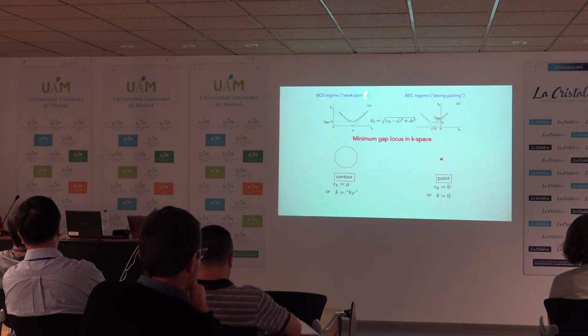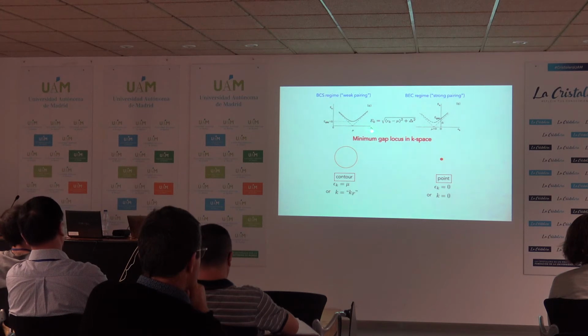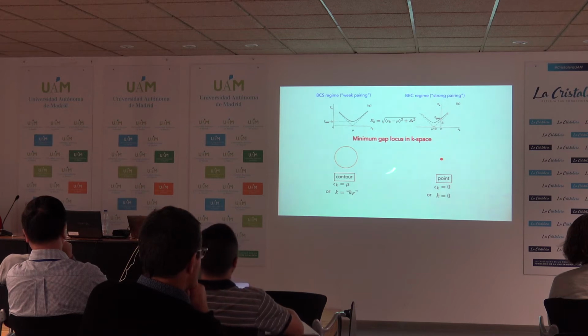This is what you are familiar with. This is the energy as a function of momentum or as a function of the bare energy. And you can see it is just linear far away from the chemical potential, and then there is this bending right around the chemical potential. So if you look at this minimum gap in momentum space and map out that contour, it's going to be a contour which has a size of the Fermi energy, and it's a closed contour.